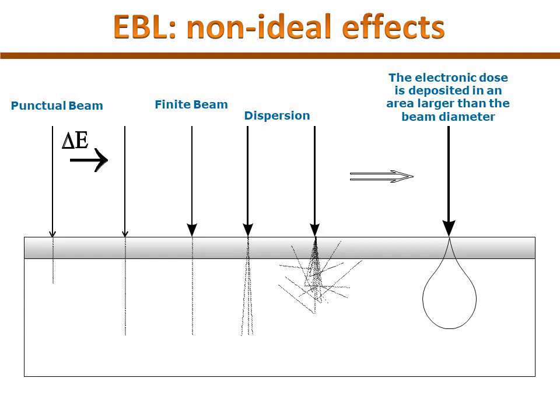There are some non-ideal effects related to the e-beam process. One is the dispersion of the beam itself, due to collision of electrons with the atoms of the resist. This dispersion produces an undesirable increase in the minimum resolution and depends on the beam energy. Increasing the beam energy decreases dispersion, since higher-energy electrons have a lower capability to interact with atoms. However, the lower the interaction, the lesser the electron's capability to affect the resist, so the dose needed increases with beam energy.